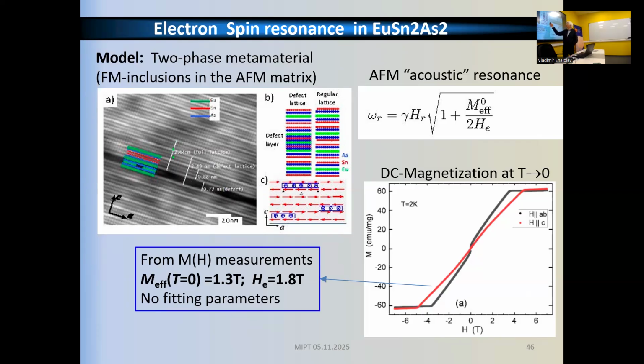So having known already the story about defects, we modeled the sample as a two-phase metamaterial where the europium layers have magnetic moments drawn here by red arrows, and in between there are some planar defects with magnetization. We don't know where the magnetization is directed, but just for simplicity, I directed them either perpendicular in this direction or in the opposite direction, and some, if they are large enough, may have a domain-like structure like that one. So we have a model, and we apply this model of a two-phase metamaterial. I assume that the subsystem of the defects and the subsystem of the host lattice don't interact, they are independent, but in fact this is a very naive approximation.